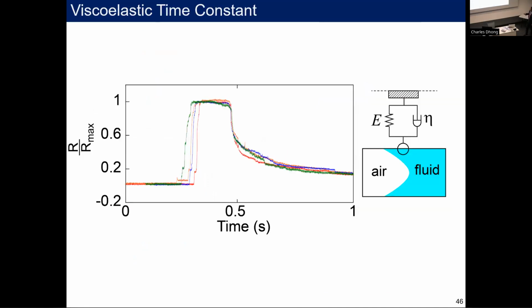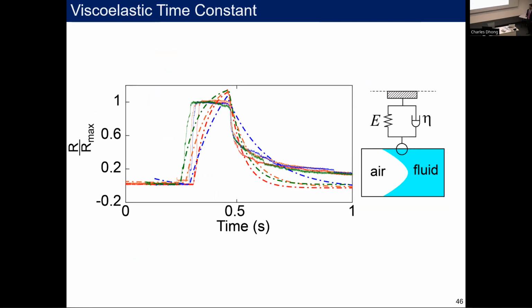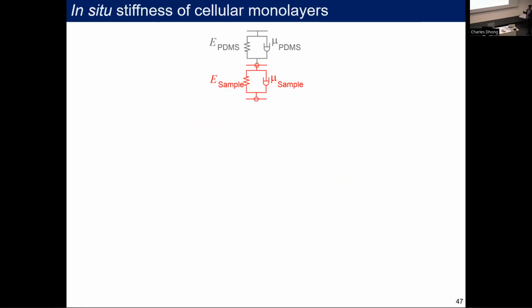So from here, we can take this and plot this against a simple spring and dashpot model and extract viscoelastic constants. And from here, we get pretty close to literature values, I would say, where we just fit this very simple model to this deformation profile. But the way we can really use this is that this reports on everything inside the channel.